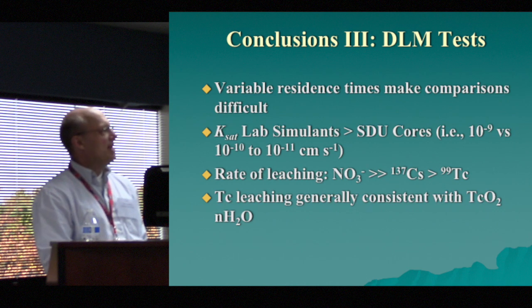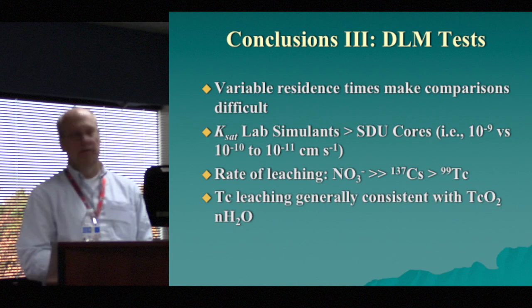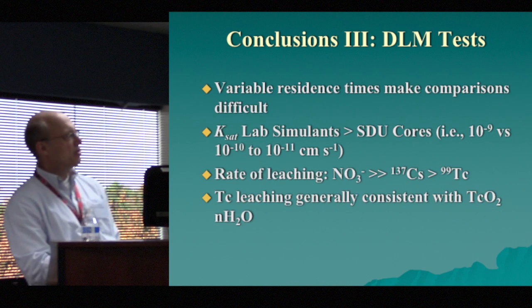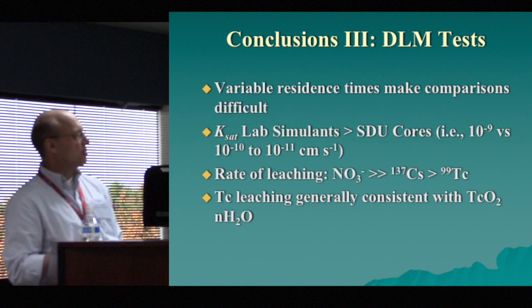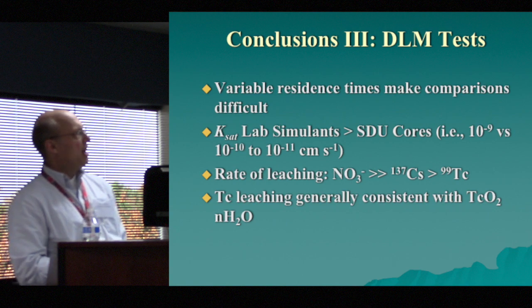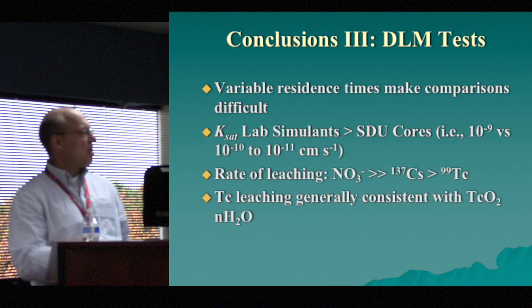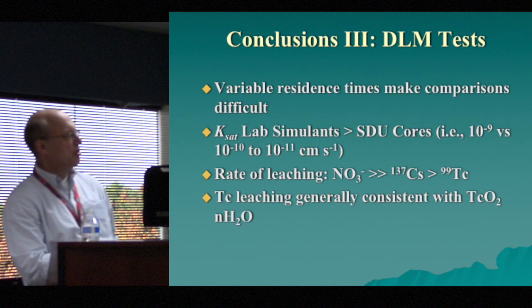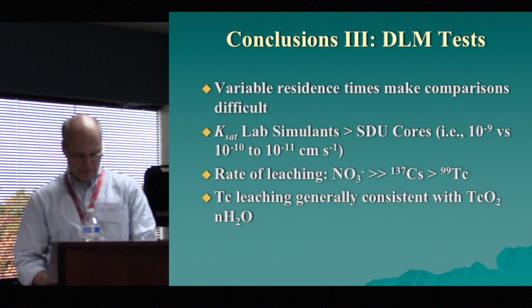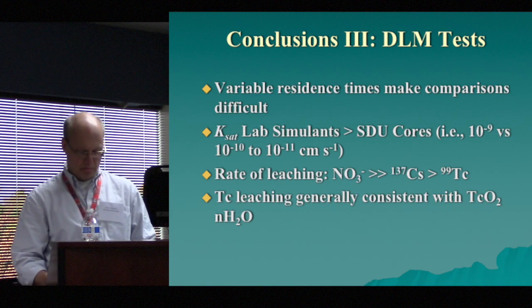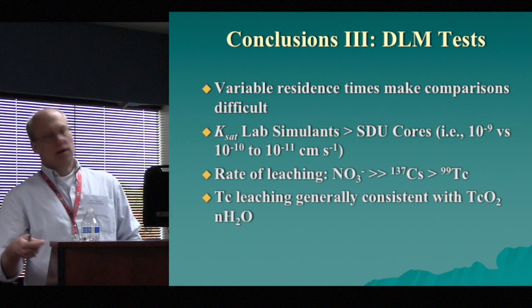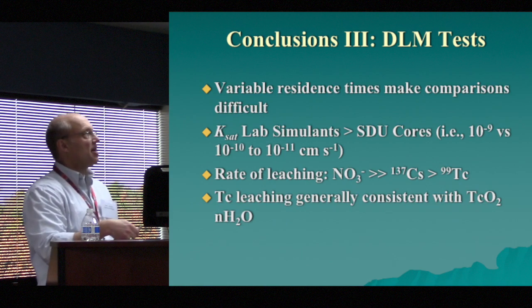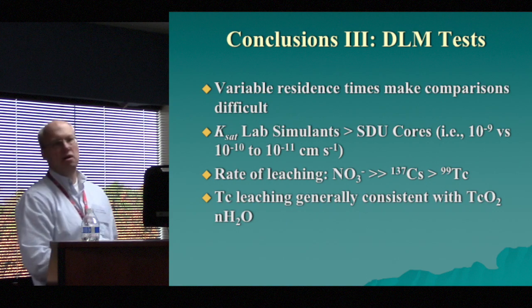The rates of leaching generally followed what we would have expected. We have nitrate coming out of there much, much faster than cesium-137, which is coming out faster than Tc-99. And though we have some increases that are hard to interpret, it's generally consistent with the Tc oxide form that we talked about earlier. So how do we fix some of these? Next slide. How do we fix some of these problems? Yeah, next slide.